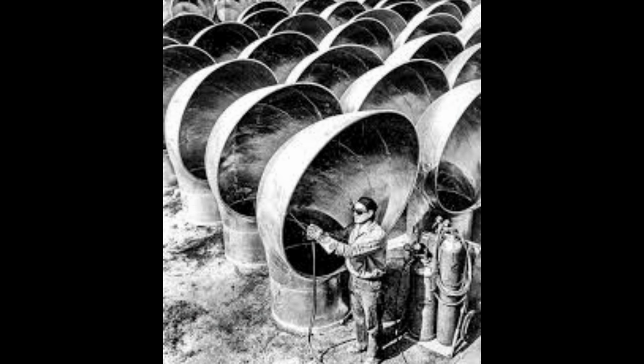The welding order was effectively torturing the steel, trapping massive residual stresses in the structure. Every seam added invisible tension that concentrated at sharp corners and hatch edges, the exact spots where ships were failing. When Liberty ships hit the frigid North Atlantic, the steel turned brittle. Those locked-in stresses combined with the cold to create perfect conditions for catastrophic fractures.